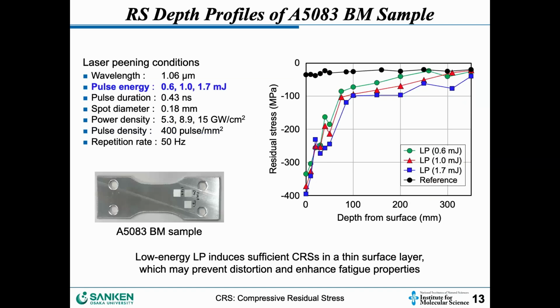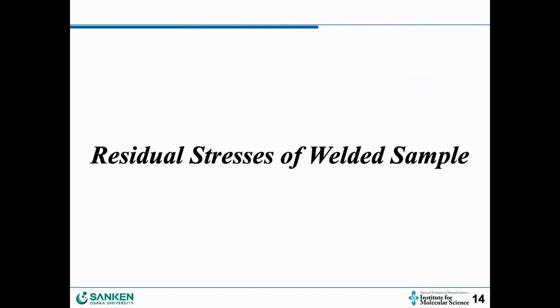So this one is a depth profile. Again, in this case we use 0.6, 1.0 and 1.7 millijoule, pulse density is fixed at 400, and spot diameter is 0.18. So low energy laser peening induces a sufficient compressive residual stress in the surface layer, which may prevent distortion and enhance fatigue properties. So we confirmed the residual stress of the welded sample.